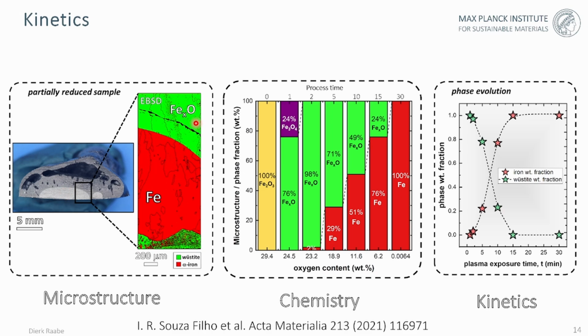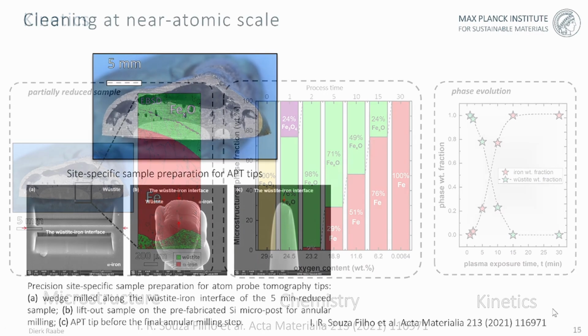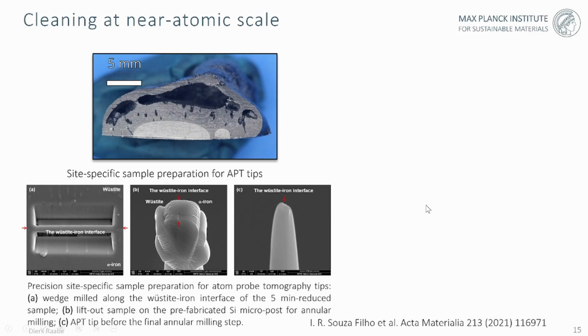Now here, of course, in the solidified state. And you can see how the fraction of the iron recovery is growing after a process time of 1, 2, 5, 10, 30 minutes, and so on. So it's a very, very efficient and very, very fast process, as you see in these kinetic diagrams. So it's extremely quick.